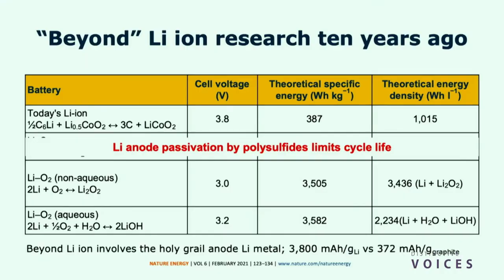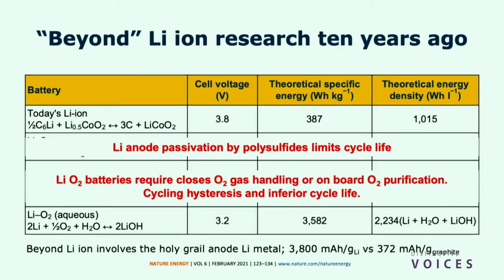Each one had its own issue. That rust layer that I described for the graphite anodes, it's even more severe with lithium sulfur. These polysulfide molecules would migrate over to the lithium electrode and passivate it. So the cycle life of a lithium sulfur battery is not so good. Lithium oxygen non-aqueous, that means you cannot have any ambient air, can't have any CO2, no nitrogen. You have to have a closed system, basically. The vehicle has to carry its own pure oxygen or have an onboard oxygen purification system, and that's just not practical.